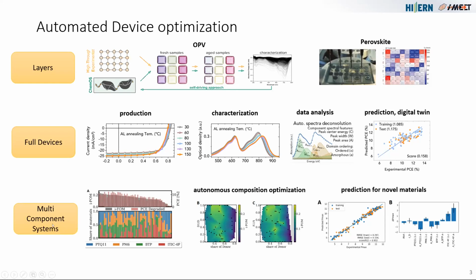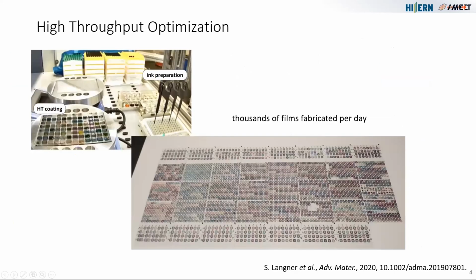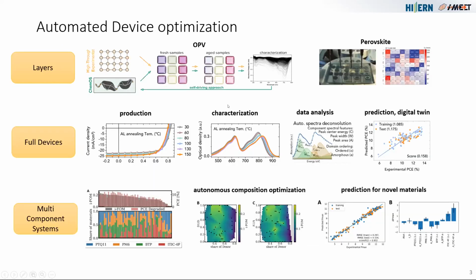And the third step in our evolution of basically robot-assisted stability tests is that we are now going to multi-component systems where we are automatically fabricating full solar cells. But now we are not only changing process conditions, we are also changing the composition. So, for example, here we have made a quaternary system, and then we are trying to use all of the information that we've learned from different correlations and from different machine learning based predictions to then optimize those multi-component systems. This is work being done by Tobias Osterrieder and also Larry Lua. So I'm going to walk through those three steps in a little more detail.